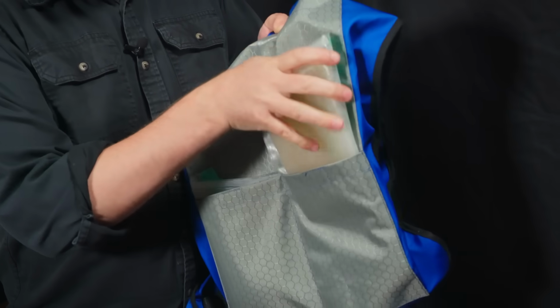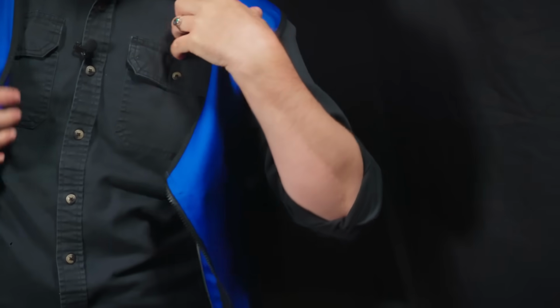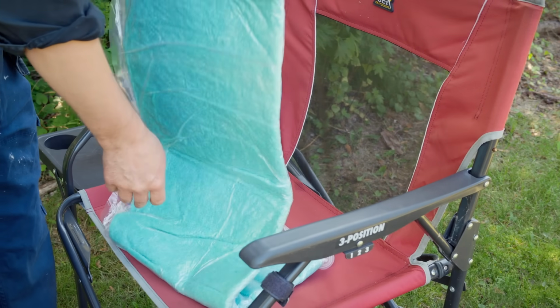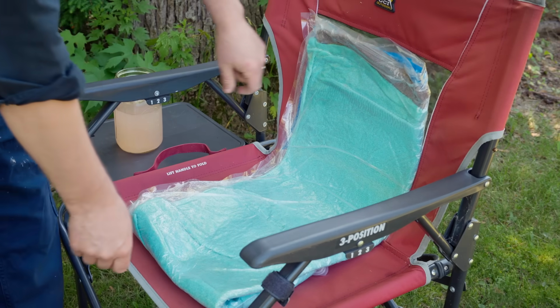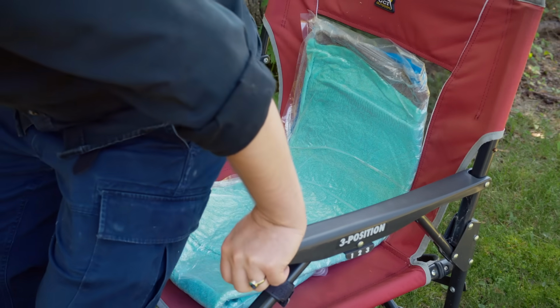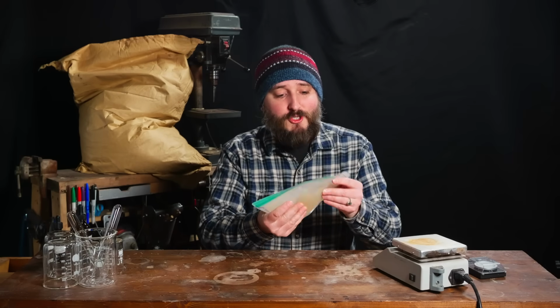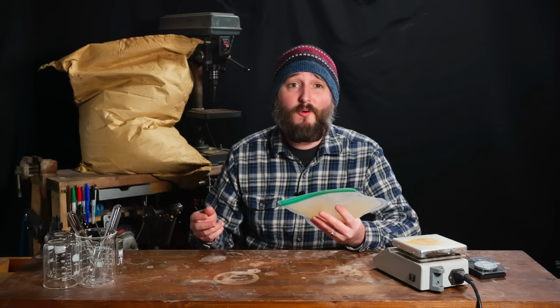In my early experiments, the focus was to use this mixture in personal cooling packs, which naturally mixes and agitates the PCM anytime you pick this up to use it. Motion prevents large crystals from forming or settling, and so the issue is avoided.